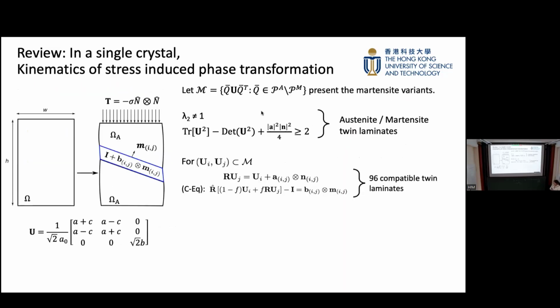And then we put it through a stress-induced uniaxial compression test. Before that, I want to give a little review of how we treat the single crystal under stress. Suppose we have a domain, which is a pillar here. And then we have the transformation stretch tensor. In austenite, we have the identity. And when we compress it uniaxially, it develops these twin laminates here.